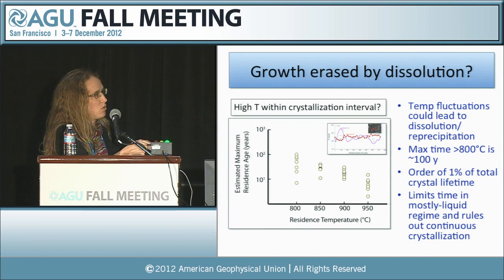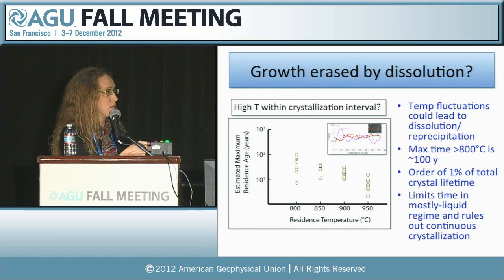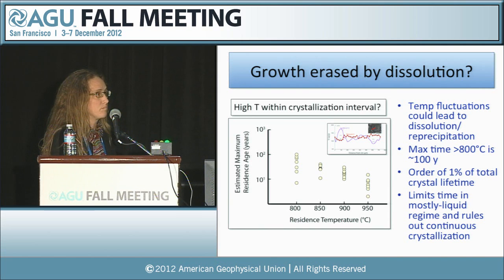So if you calculate, for example, a residence temperature of 800 degrees, these are data for individual crystals, for individual profiles like this that Adam has modeled. And the estimated maximum residence age at 800 is on the order of decades to maybe centuries, which is still on the order of about 1% of the total crystal lifetime. So these kinds of arguments we can make. This limits how much time these crystals could have spent in this upper temperature range between the liquidus and solidus, in this mostly liquid regime. And it also rules out continuous crystallization, unless you're going to call upon growth rates that are incredibly slow and that it was spending its crystallization at the sort of near solidus conditions.